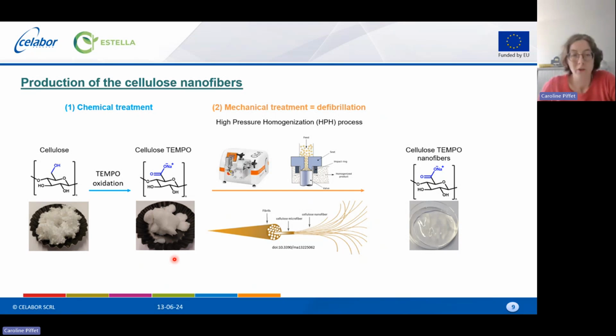And then when we have this pre-treated cellulose, we proceeded to a mechanical treatment, the defibrillation, in order to have nanofibers. So the cellulose is composed of fibrils, which are composed of microfibers, which are composed of nanofibers. And with the mechanical treatment, we will destroy and separate the nanofibers one from the others to obtain separate fibers, as we saw in the previous presentation.